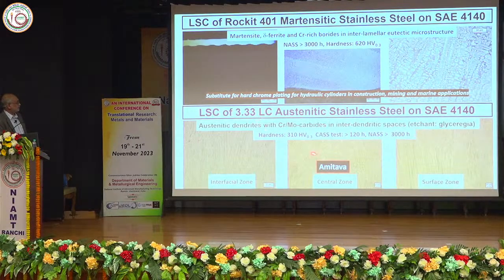This is what Amitav Roy is trying to do, and his work is related to two varieties again, austenitic and martensitic. He wants to develop austenitic dendrites with carbides in between, in the interdendritic spaces — essentially creating stainless steel on 4140 as a base, and developing either martensitic or austenitic variety onto the surface, so they can be used for conditions where the threats from wear and erosion are much larger.